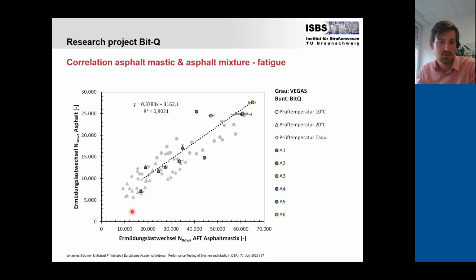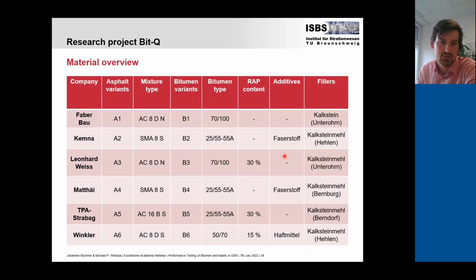For fatigue testing, the same applies. We now checked only two different test temperatures, 10 and 20 degrees. We can see the results from 10 degrees here, again overlaid on the results from the previous research project. All 6 materials can be differentiated. For example, you can see that variant number 1, the dark blue one, has the lowest number of fatigue load cycles, and actually this number 1 was the softest binder. Now when I go back, you can see that number 1 was the one with only the 70/100 and no RAP content.